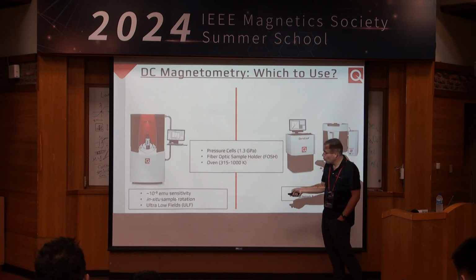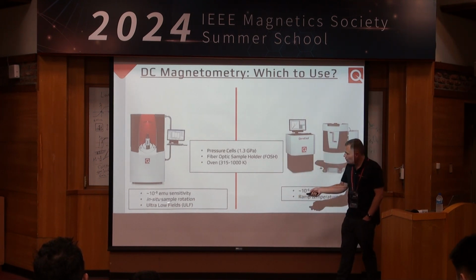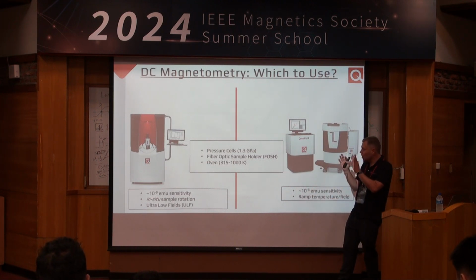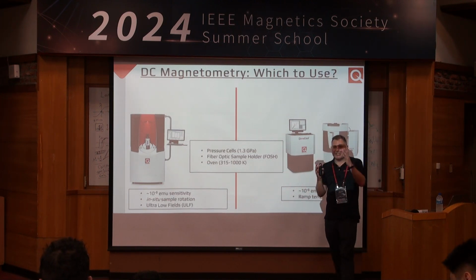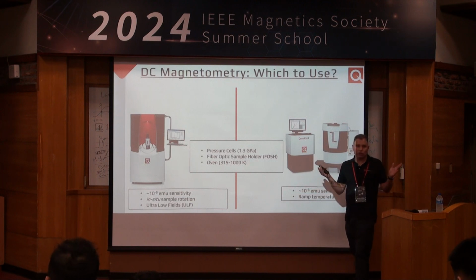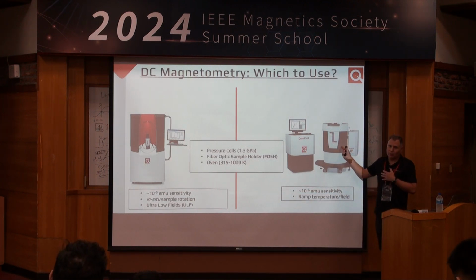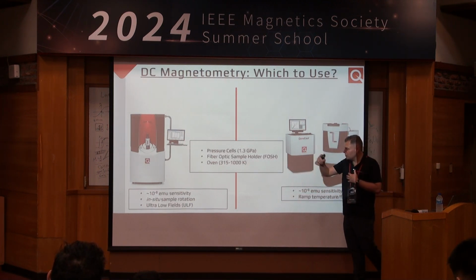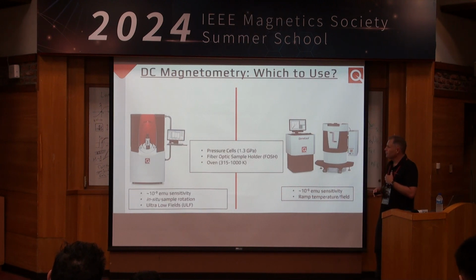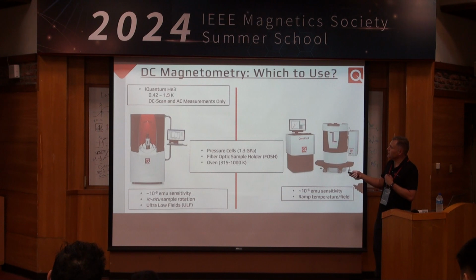But here we actually have a way to rotate our samples in situ. Here we cannot do that. Here we have an ability to actually measure very low coercive samples. Let's say you have a YIG film with coercivity of an Earth's field. You basically can't do it in a system like this. A system like this, you can. Another nice thing about this system, we have a special insert so you can measure all the way down to 0.42 Kelvin. It's basically a helium-3 refrigerator.